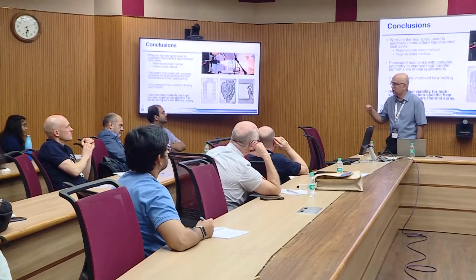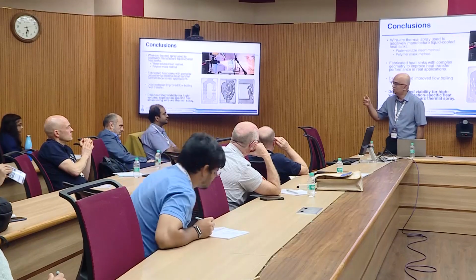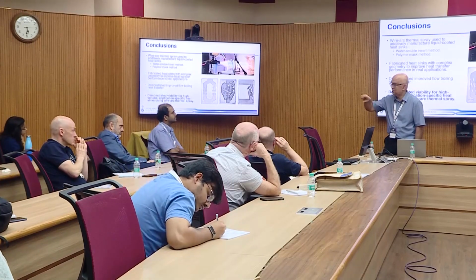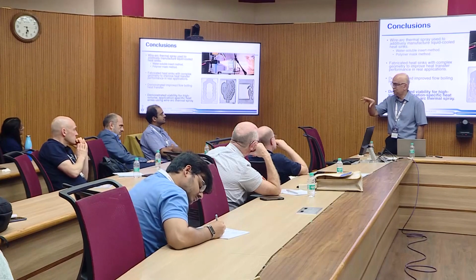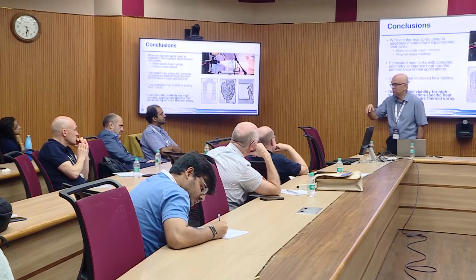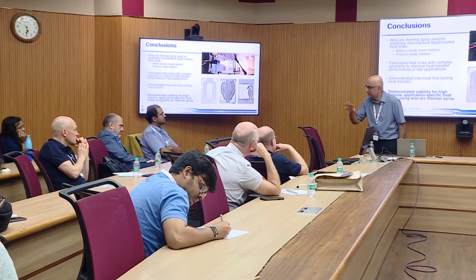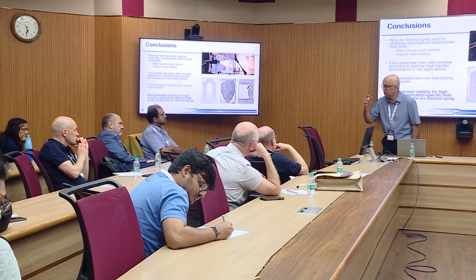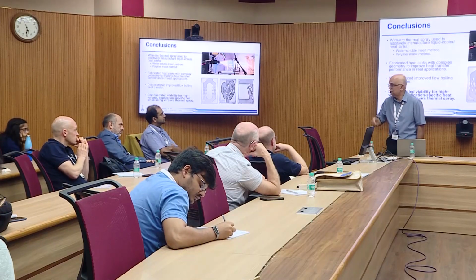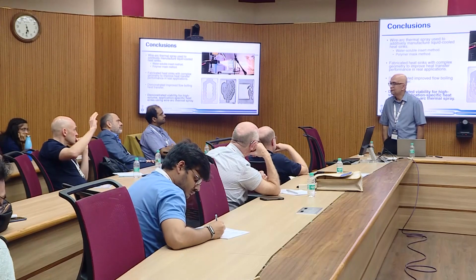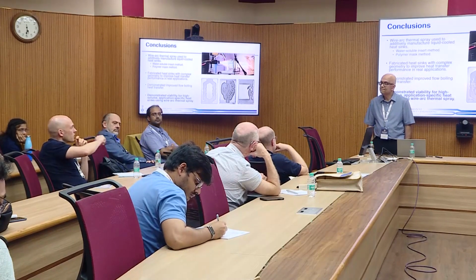You can't use the water soluble material. They're not really designed to do that. They use the water soluble as their sacrificial material when you're trying to make voids inside. So we've got an open source one which we can mess around with, and we can put anything in it. We put the PVA in and print it out with that as well.